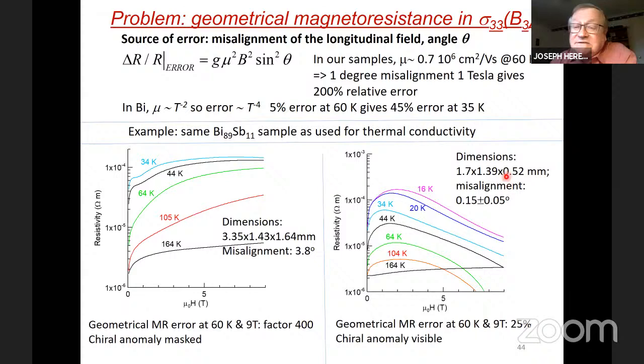If, on the other hand, we take the same sample, we cut it down, we cut it very narrow, we put the length to width ratio now on the order of 3:1 instead of 1:1, and we keep the misalignment at 0.15 degrees, the error we estimate from this little formula is now 25%. And now we see the negative magneto resistance that's supposed to be the signature of the chiral anomaly. But still, the error bar is still on the order of a substantial fraction of the measurement.